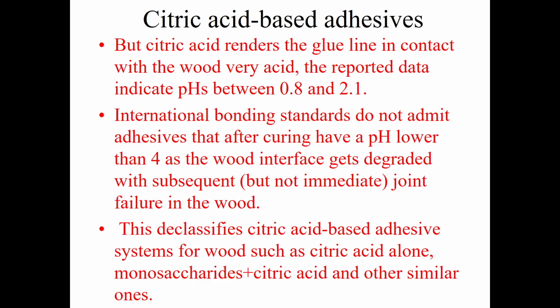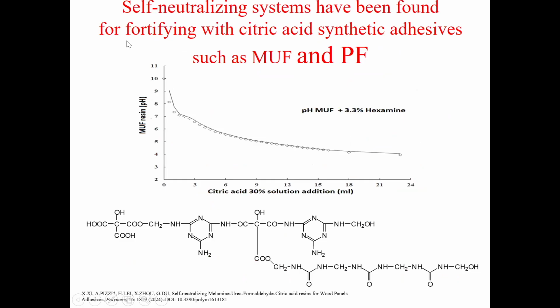This declassifies citric acid-based adhesive systems for wood, such as citric acid alone, monosaccharides plus citric acid, and other similar ones. But we found a remedy for this, because the system is too interesting to let it drop. Now, we can have, for instance, melamine urea formaldehyde and phenol formaldehyde resin with citric acid. And melamine UF resin, when you add 3.3% of hexamine, a strong buffer, actually maintains the pH well above 4. So you have the citric acid that contributes to the reaction,